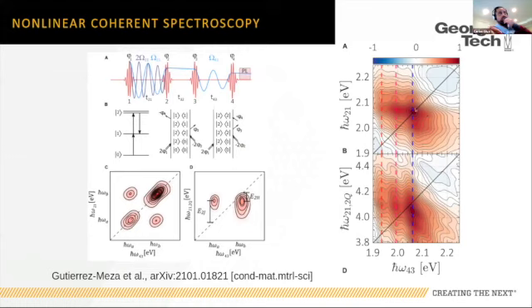Now, I don't have enough bandwidth to really cleanly see 0, 1, but I do see these cross peaks between 0, 0 and 0, 1. That's what I expect. But I also see some very weak structure at lower energy in the diagonal, and then I see strong cross peaks with the structure.